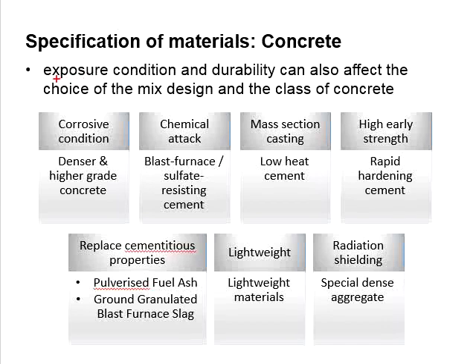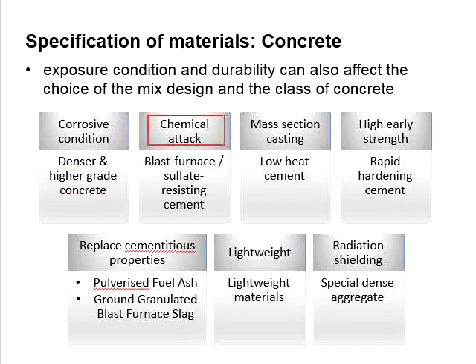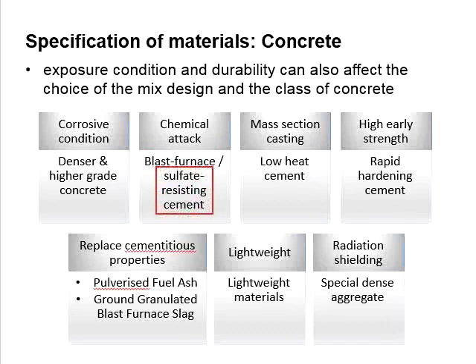The exposure conditions of the concrete can affect the choice of mix design and the class of the concrete. For corrosive conditions, denser and higher strength concrete are normally used. To prevent chemical attack, the amount of cement in the mix can be reduced and replaced by other forms of cementitious materials, such as blast furnace slag, or sulphate-resistant cement can be used.